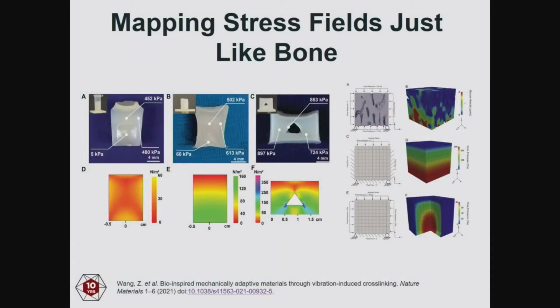We got a little clever. We started punching holes inside of it so that when there were little points in the triangle, we would get very large stress fields that would concentrate at the edges of the material as we were vibrating it. And we could see then that when we put little indentations in here and sampled the different points, and you could even see here where the polymer is actually spontaneously forming at the edges of the stress fields, the material would respond by basically mapping the stress field that it was experiencing, exactly like the bone was doing.